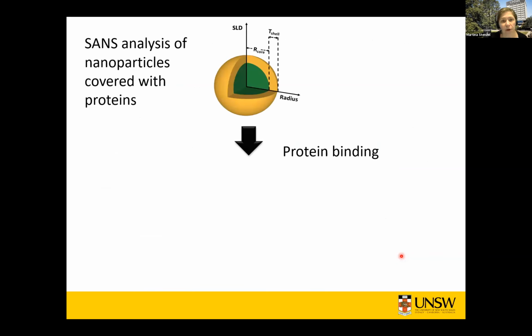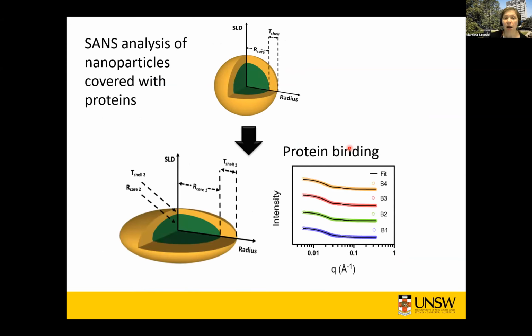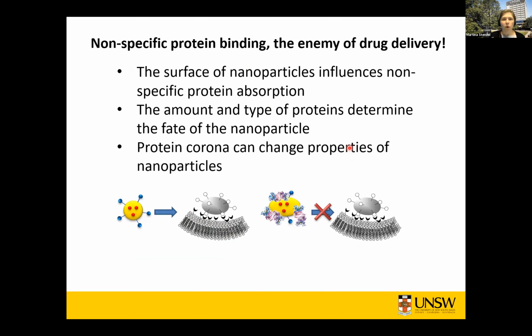However, what happens on top of it is not just that we have a layer of proteins on the surface, but also this protein might now do something to these nanoparticles we don't expect. In that case, we found that our proteins managed to deform these nanoparticles, and we suddenly got spheroid particles. And that's really quite important to understand, because round particles have a very different cellular uptake pattern to spheroid particles. So what we really found is that when we have nanoparticles, we need to always consider that these nanoparticles might not be able to do their targeting jobs as we expected.